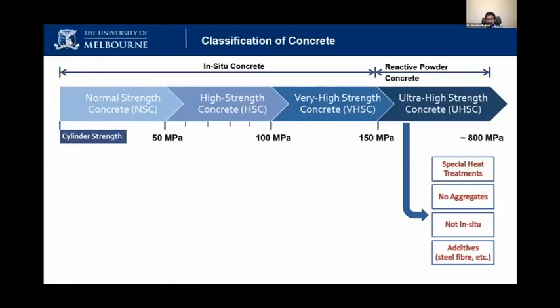So if I give a brief outline of concrete, it can basically be divided into four categories as shown in this slide. We know normal strength concrete, we have good understanding. Now we know high strength concrete, we use that for structures. Getting something more than 50 is not a challenge anymore with super plasticizers and silica fumes. That changed a lot in the industry because with super plasticizers we can easily reduce the water to cement ratio, and further, the voids in the microstructure can be filled using silica fumes. So we can easily achieve somewhere around 50 to 100.